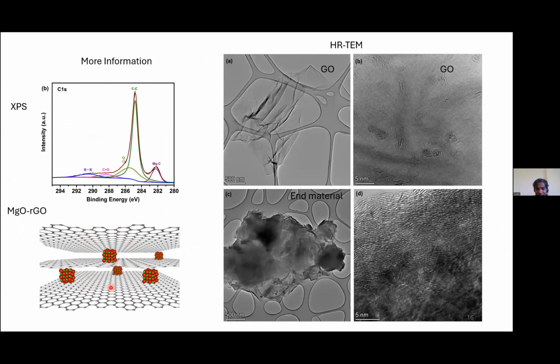Basically, the assumption was this. If it's so, we are happy. Anyway, you need expanded interplanar spacing. And XPS investigations further proved that you have magnesium-carbon bonding along with the magnesium-oxygen bonding that was proven previously. And graphitic nature is there, C-C. And the pi-pi* shake-up peak says that it can be a layered structure and functional attachments are still there. So it's all giving more and more value to our assumption that something interesting, like a pillared structure, may happen. It may not be a perfect structure as we assume, but at least some pillaring activity could have been